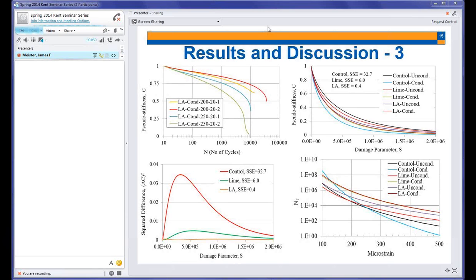Now, for the control mix, we had two cases. At lower microstrain, the number of cycles to failure for the conditioned is higher than the unconditioned. But when we went to higher microstrain, things became more logical, where the number of cycles for the unconditioned is higher than the conditioned. And this is another conclusion. Maybe if we need to compare the same mix between its unconditioned and conditioned states, we need to use two different microstrain: a lower strain for the conditioned and a higher strain for the unconditioned, in order to compare apples to apples.